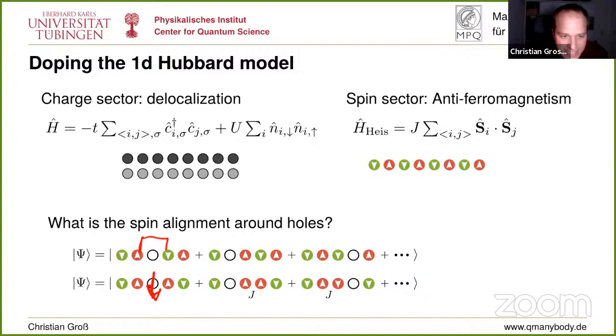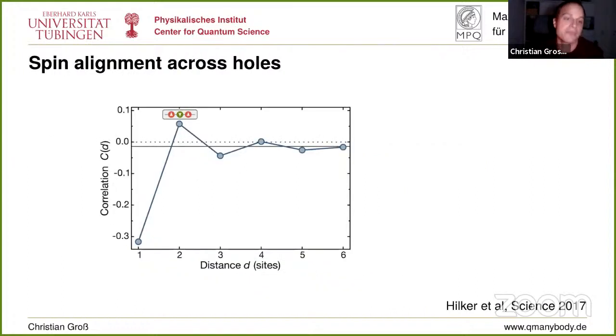If you do that in this case, you move the hole, then you get 2 upspins and you pay J. Right, so this shows you already that in 1D, actually, there's a way of making spin and charge degrees of freedom at the same time happy. And you will see that this is actually the origin of why they don't care for each other really in 1D. That's spin charge separation.